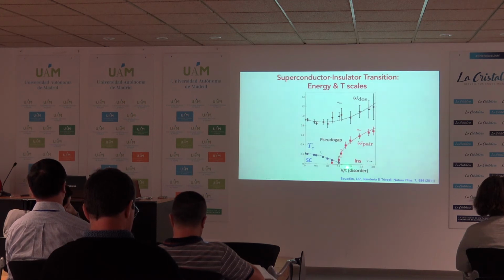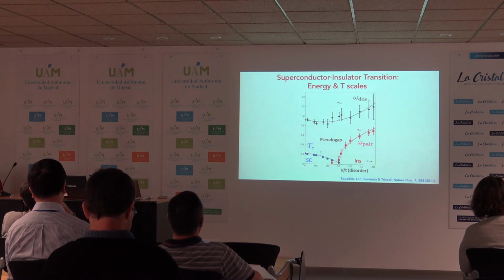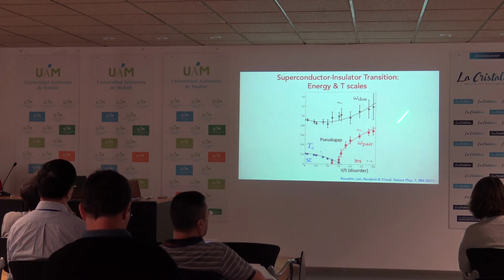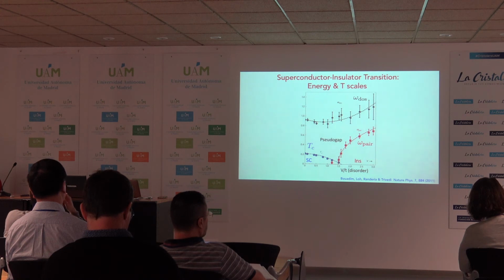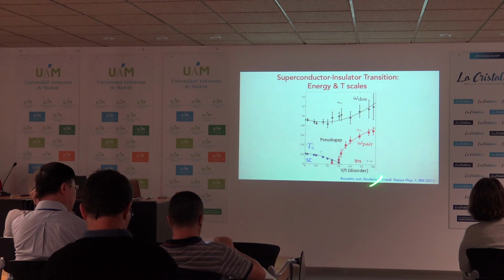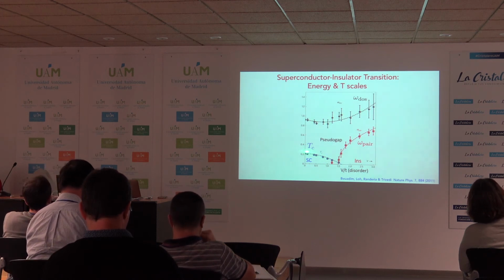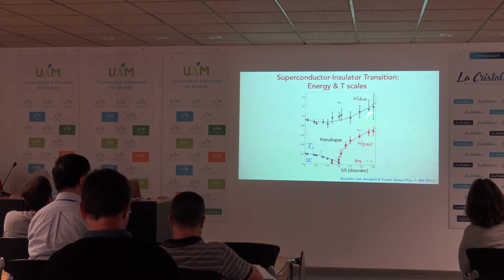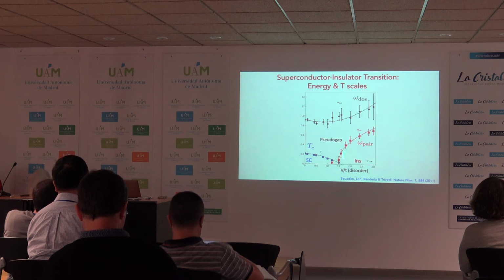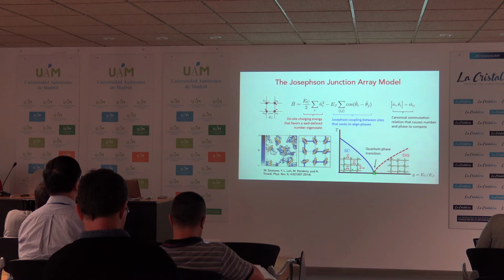And what we find in our case, we calculate this, that energy scale to add a pair into the system goes soft precisely at the quantum critical point. So this then summarizes basically the disorder-driven SIT. The single particle scale is always finite as a function of disorder. On the superconducting side, Tc is becoming small, and this Tc itself is interesting in terms of whether it is determined by amplitude or phase. Close to the transition, it's determined by the phase. Far away here, it's determined by the amplitude. And then entering the insulator, the two-particle gap is of course 0 everywhere in the superconductor, but it starts increasing with some exponents here toward the insulator. Okay, so that's the situation of part 2.